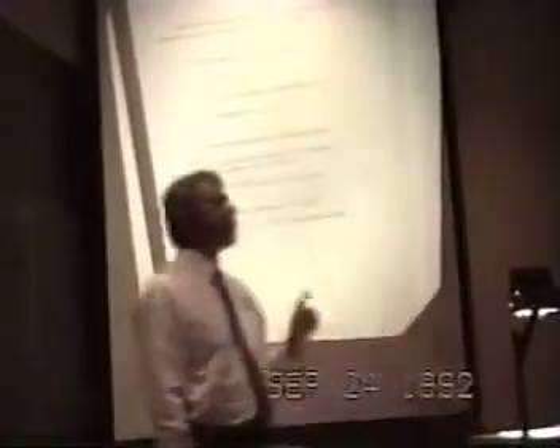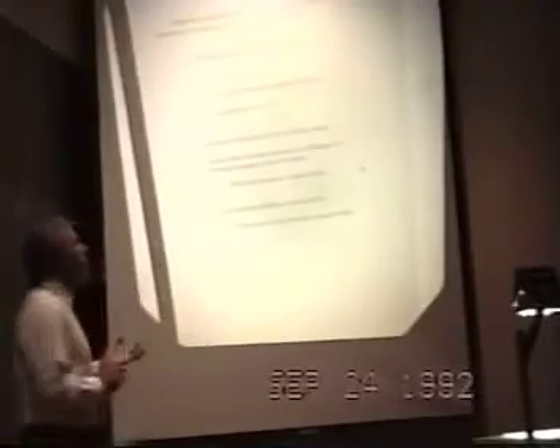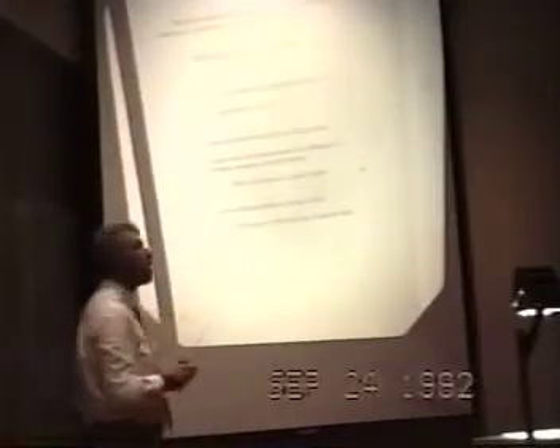The baseline observations themselves appear with a reproducible pattern, and they are observed if a minimum of 3 criteria are met. The deuterium-palladium ratio must achieve a critical value, a value something like 0.9 D to Pd. Above that, there is a parabolic or possibly exponential increase, and I'll show you some plots of that functionality later, with increase in loading, possibly asymptotically reaching an asymptotic limit at a value of loading of 1, possibly.